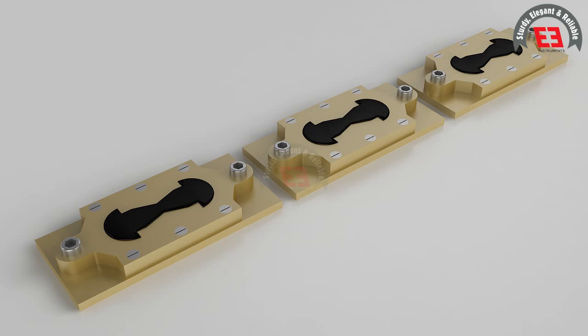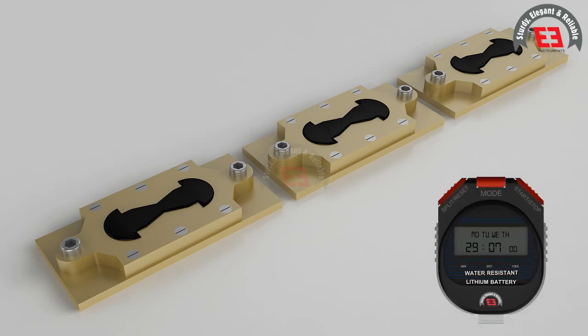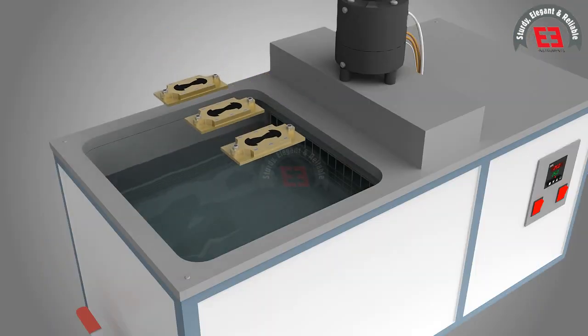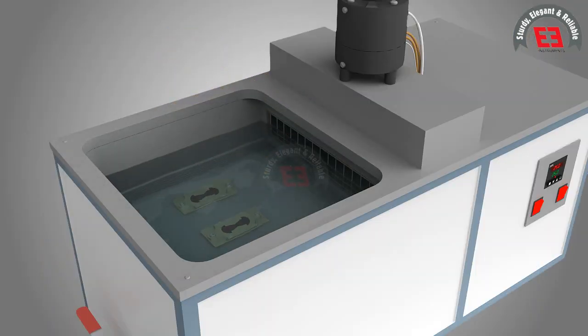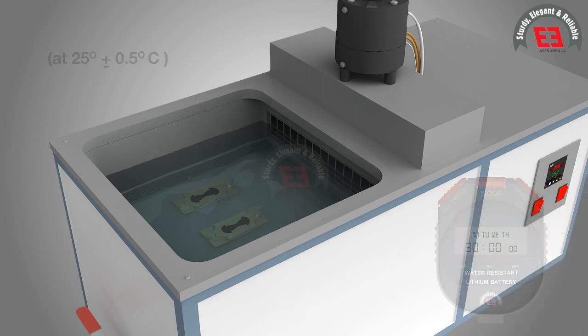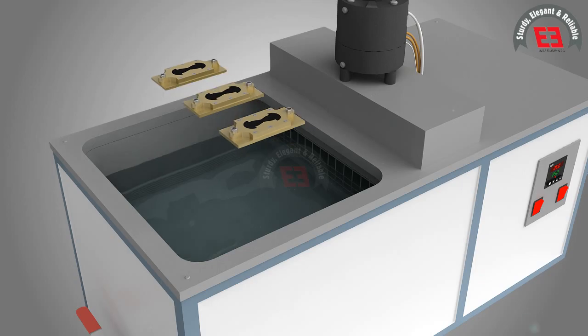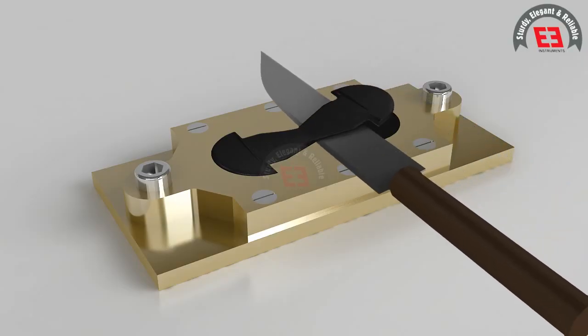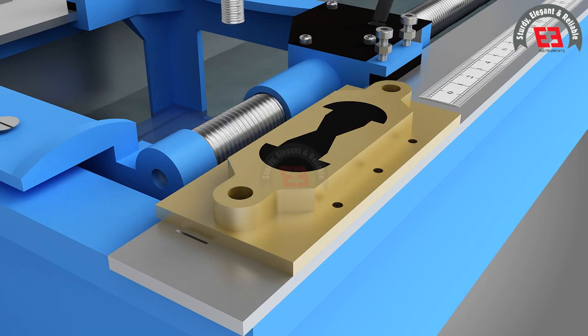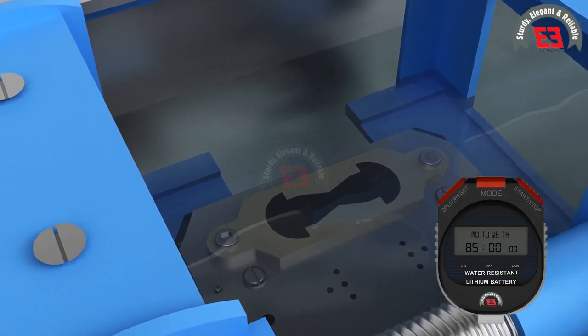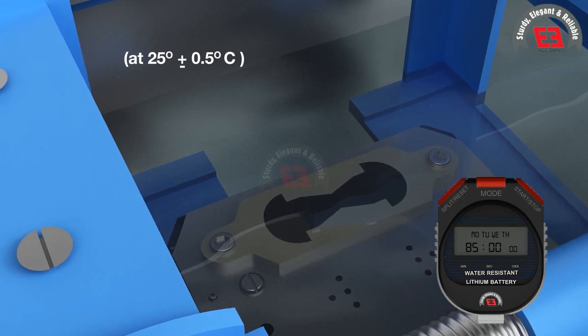The molds along with the plate assembly and bitumen sample are kept at room temperature for 30 to 40 minutes. The air-cooled specimen is then kept in a water bath maintained at 25 degrees Celsius plus or minus 0.5 degrees Celsius for 30 minutes. Thereafter, the sample and mold assembly are removed from the water bath and excess bitumen is cut by hot knife. After trimming the bitumen sample, it is placed in the ductility machine for 85 to 95 minutes at 25 degrees Celsius plus or minus 0.5 degrees Celsius.